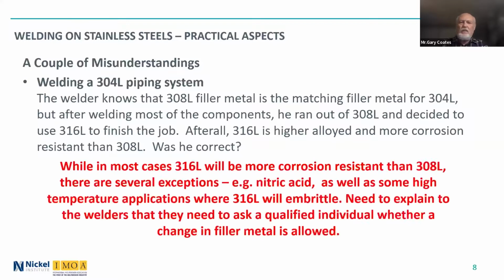Well, in most cases, 316L is more corrosion resistant than 308L, but there are several exceptions, one of them being nitric acid, where 308L, 304L is more corrosion resistant than 316L. And there are some high temperature applications where 316L will embrittle, where the 308L will not embrittle as quickly. So we need to explain to welders that they need to ask a qualified individual whether a change in filler metal is allowed. Now, if you were doing something very strict in the nuclear industry, there would be probably no question about the welder changing the filler metal on his own. But in many plants, and especially when there are fewer people around, he may make the decision himself.